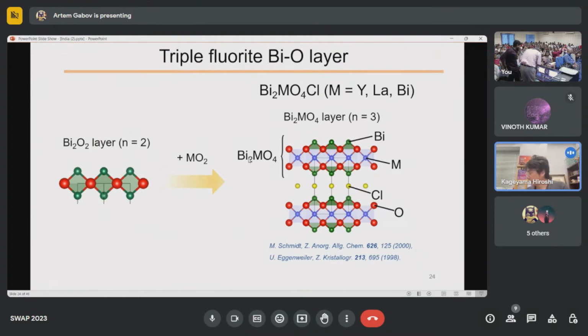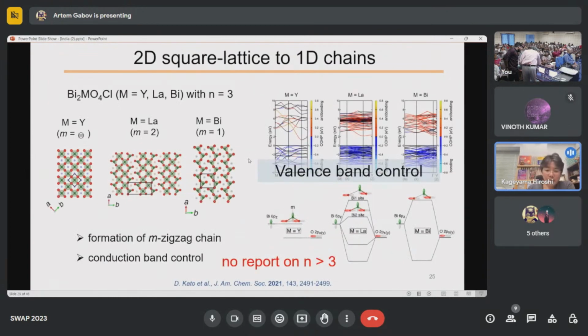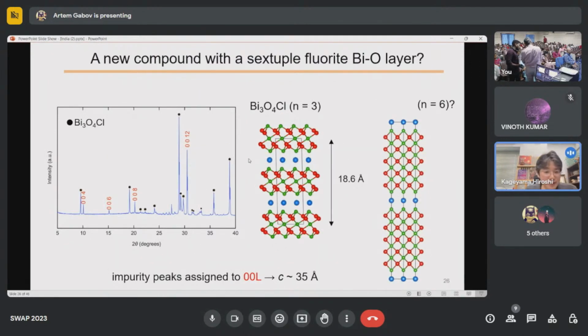Then we found that these compounds show the ability to control the valence band, as you can see here. But I don't want to go into details, so you may take a look at this paper published about 2 years ago. In the course of characterizing the structure of this bismuth material, we found unwanted impurity phases. This was a problem in the initial stage of our research. After that, we focused on this material and tried to determine its structure. Then we found that this unknown compound has a C-axis lattice parameter of 35 angstrom,